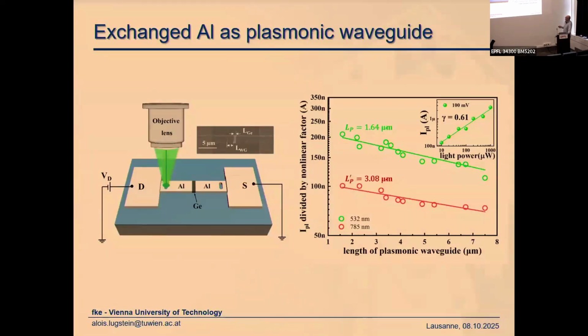So we did a detailed investigation where we made these devices where we kept the length of the germanium segment constant, but we varied the length of the aluminum waveguide. This is shown here for red and green light. And you see that the current, of course, decreases with the length of the plasmonic waveguide as you have more and more damping and you lose the energy of the plasmons. And that means you generate less hot electrons at the interface.